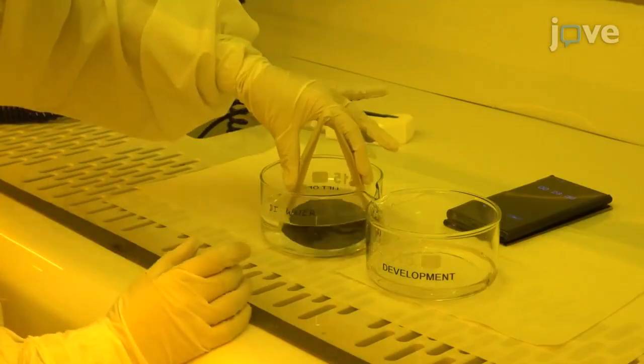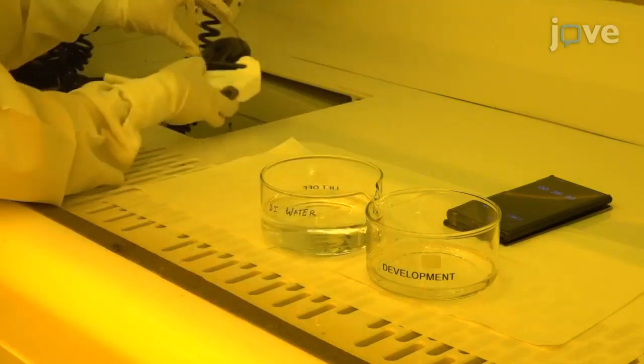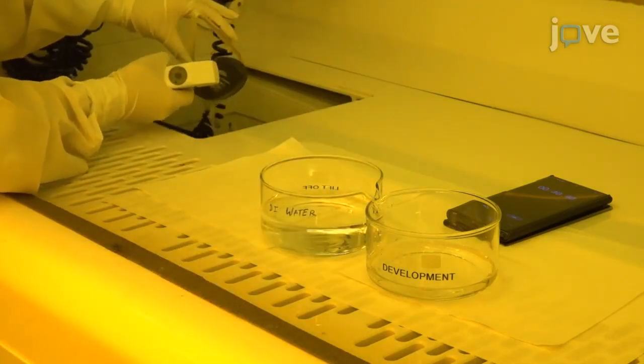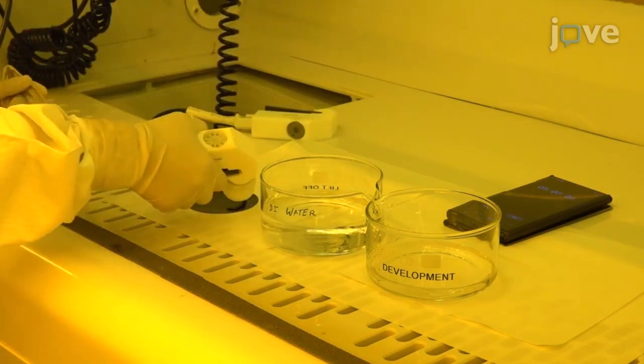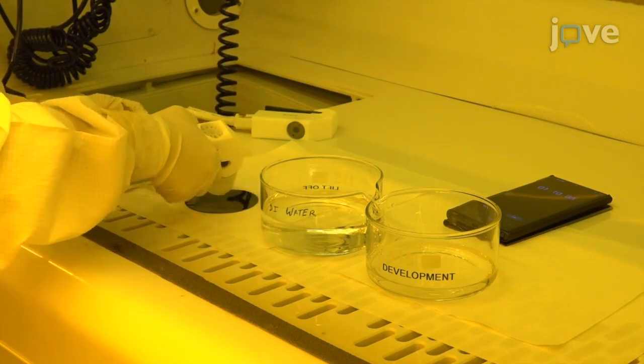Rinse the device with deionized water and use a physical vapor deposition system to deposit 10 nanometers of titanium and 100 nanometers of platinum onto the substrate pattern on layer 1. To lift off the deposited metals...